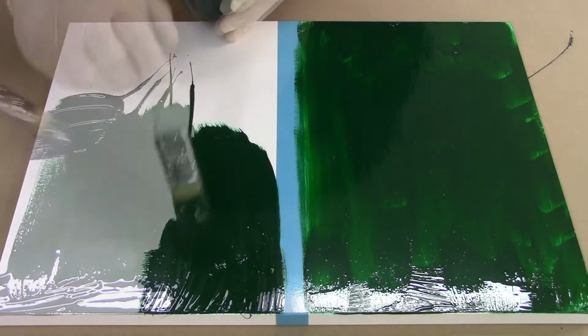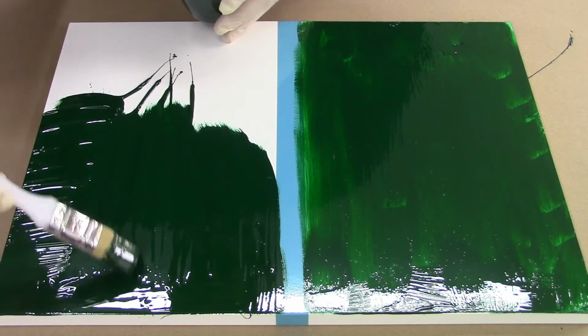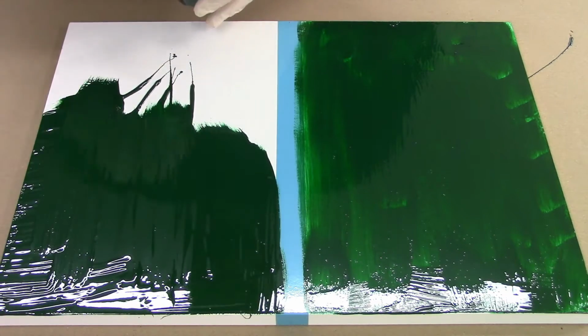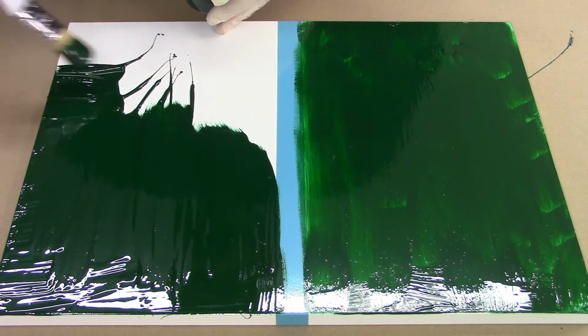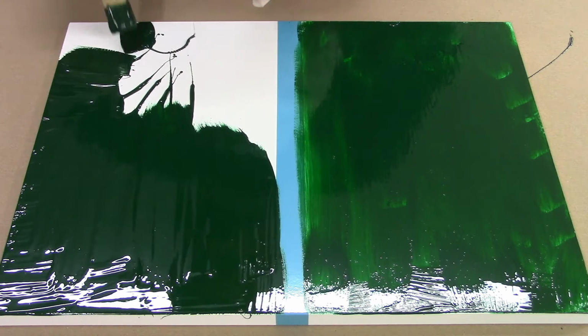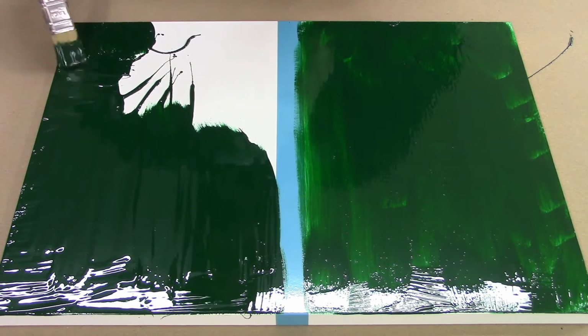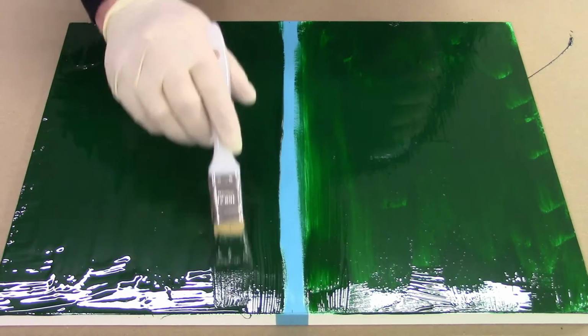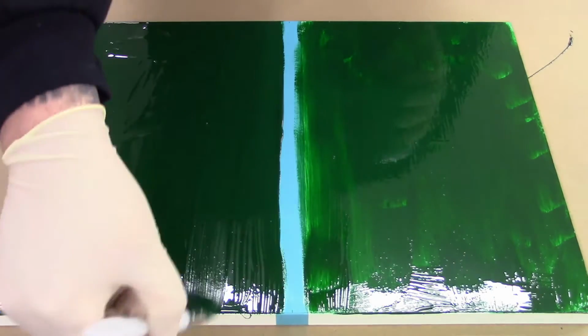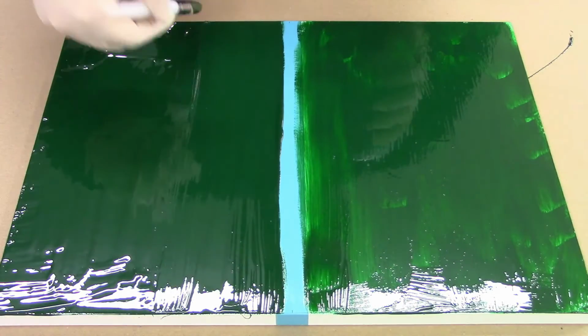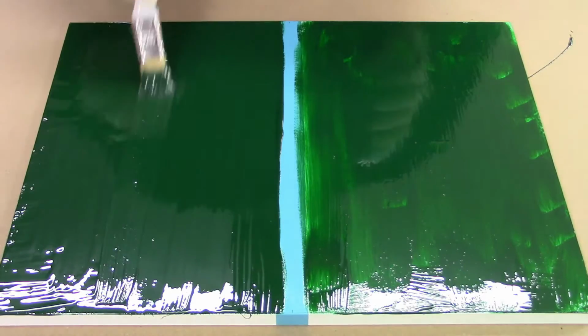You're looking for a film thickness that hides the mould, roughly around 0.6 millimetres thick. Coverage at this thickness is approximately 600 grams per square metre. Once liberally coated, it can be neatly tipped off with the brush to tidy the surface, ready for laying your fiberglass.